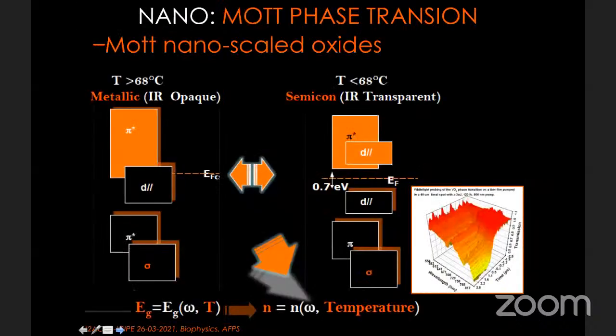We know very well now the science of it. In effect, at low temperature, it has a band gap of 0.7 electron volt. And at high temperature, this band gap closes because the d orbitals here, which were split, recombine again, and with the d band recombining, the band gap is closed and it becomes metal. And this change is reversible. What does it mean when the band gap opens at low temperature, closes at high temperature, opens at low temperature, closes at high temperature? That means there is a change of the refractive index.